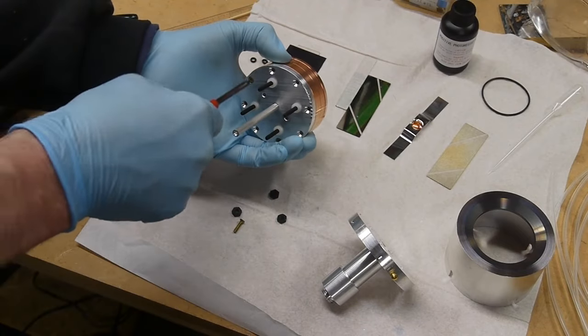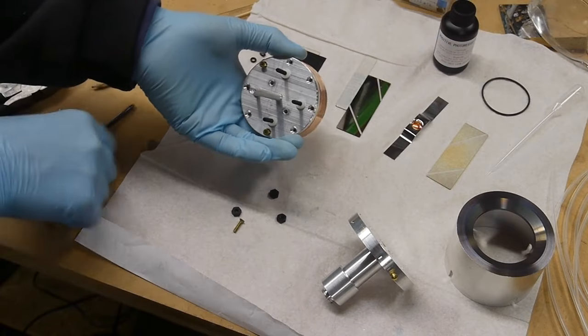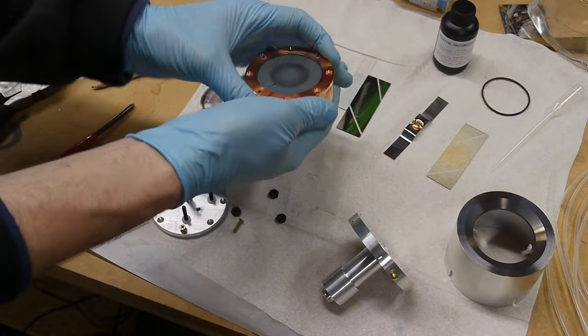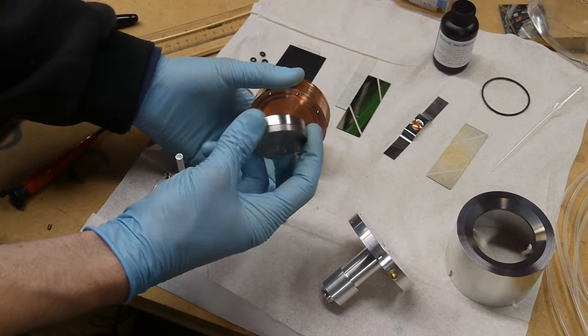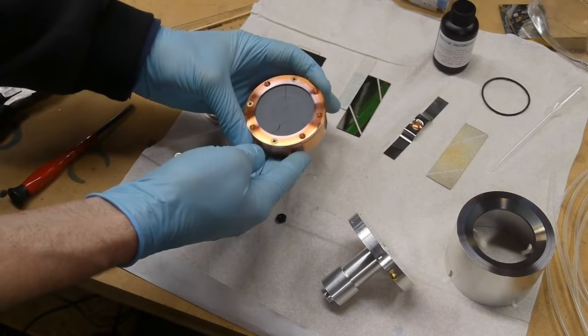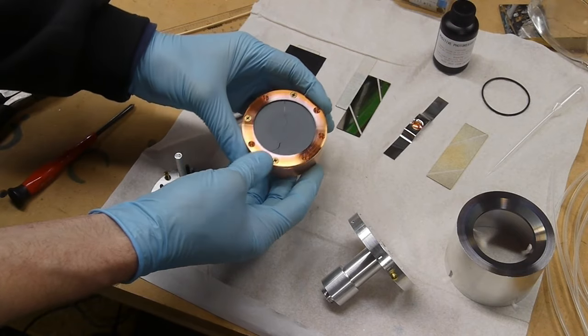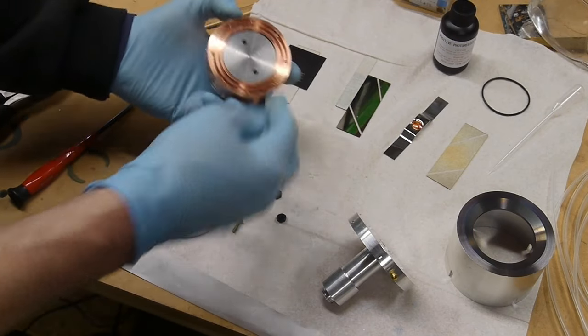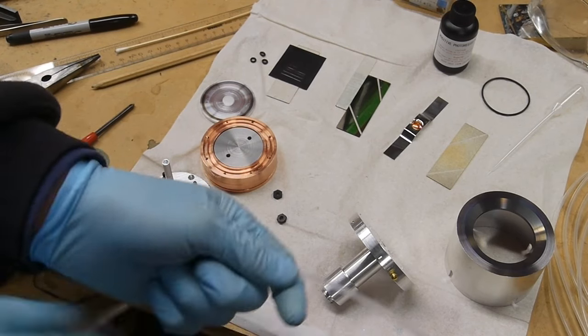So inside here we've got a very high potential between this outer shell and the inner shell, but there's a few other tricks here that allow us to sputter just the target material. I'll open this up, and as you can see I'm missing quite a few screws because I haven't got the right ones in yet. Inside here is a neodymium ring magnet and a steel pole piece that I turned on the lathe. The idea here is that when the magnet is inserted, there's a nice magnetic field on the top, and you can even see a ring pattern where the disk has been eroded by the sputtering. I've also got some holes in here for a cooling system, which unfortunately I didn't have running yet, hence the cracked disk.